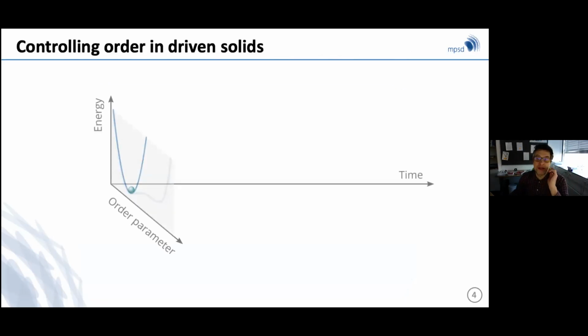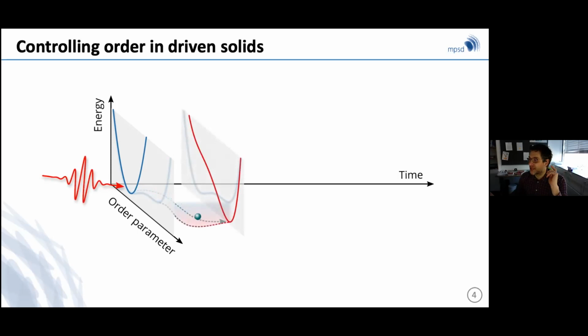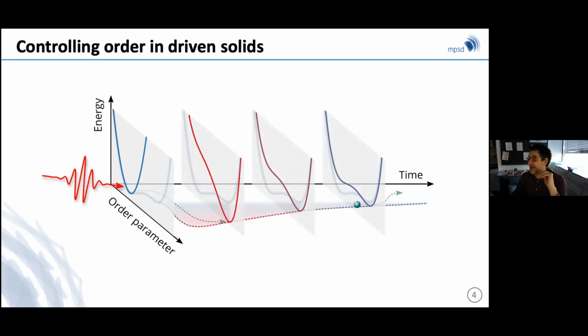So the problem will be one in which the equilibrium order parameter dependent energy is now being perturbed and results in a change in the underlying structure, which then evolves in time on a time scale that can be either slow or fast, depending on the details of the system, but where, let's say, in the red free energy that I showed there as a second plot going from left to right, one may create, for example, a new minimum of potential where new physics is being seen.